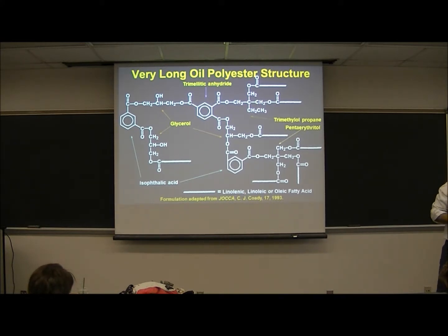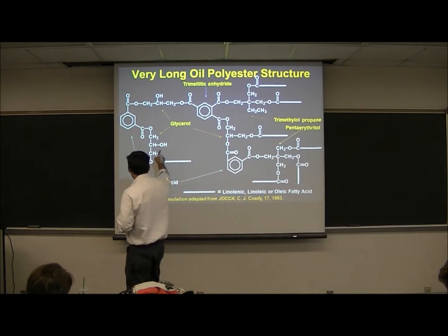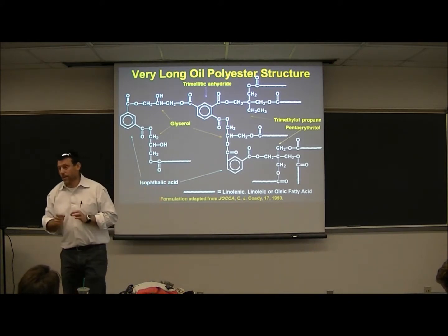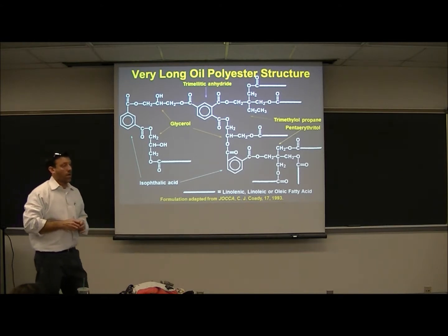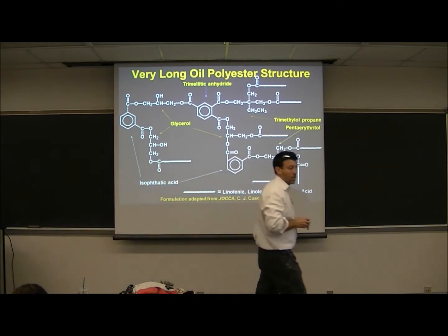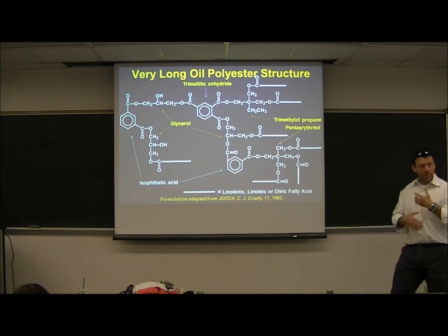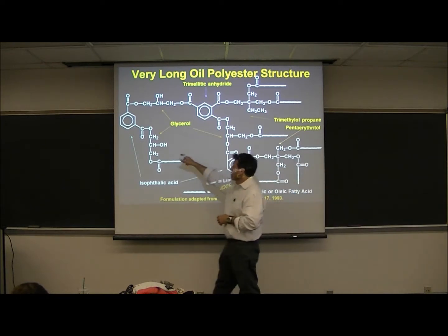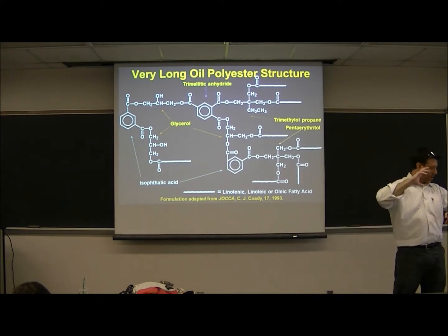It also turns out that when you make polyesters for a lot of applications, including industrial plastics, if you have free hydroxyl groups, you will better disperse colorants and pigments. It's a very simple thing, but it turns out to be absolutely critical. And most people don't buy just chunks of polymer with no color and no additive and no filler. And if you can't disperse it properly, then you get something that has what we call bleed or color drift. It'll have speckles and spots. So you have to get pigments, fillers, things like that evenly dispersed. And just leaving a few hydroxyl groups in each molecule will help to facilitate that. It's a polar entity that's good at disrupting pigment agglomeration and things like that.